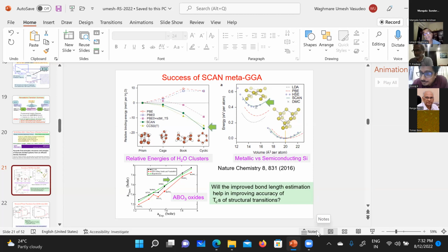No, so we did show that in ferroelectric oxides, they capture energy variance better than LDA and GGA in terms of their ability to capture experimental TCs. But I also at the same time share with you that we haven't been very successful in using it for metallic systems, metallic transition metals particularly.